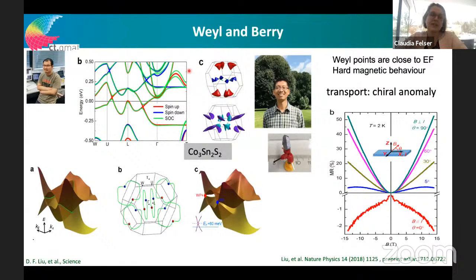You have two bands crossing at the Fermi energy, with this nice crossing point. So we have these nice, ideal Weyl points, and the red lines are spin up if you don't apply spin-orbit coupling, and the greens are if you apply spin-orbit coupling, so you have these very nice crossing points around the Fermi energy. And you have quite a simple Fermi surface because of the simple electronic structure. This compound is a relative of a semiconductor. It has one additional electron. What you see here is just one electron occupying this band, more than the semiconducting counterpart. And here you see the drawing of the nodal lines in this compound, and here are the Weyl points in the Brillouin zone in this material.